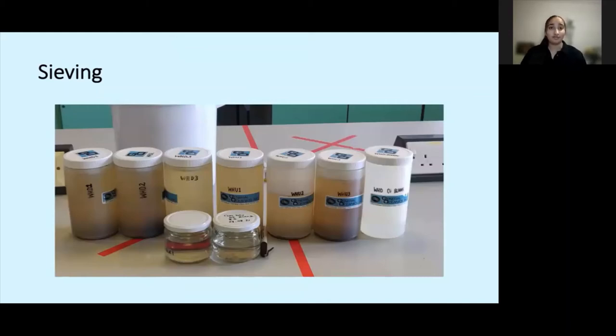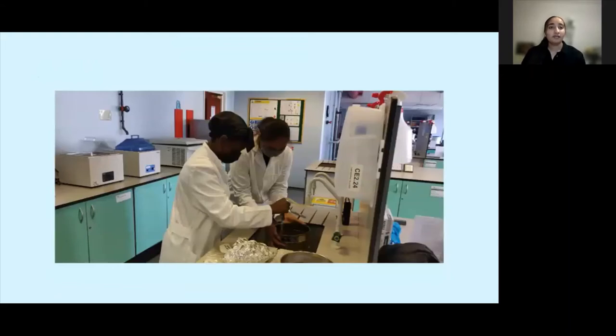The periodic blanks were filtered through filter paper and then we dried the filter paper before assessing using microscopes. If any microplastics were found present on the filter paper, we would then need to take account of this as part of the study as a potential contaminator and ensure that we were cautious when counting microplastics in our samples as they may have entered the study from other sources, such as through the filtered water or perhaps it could have been airborne.